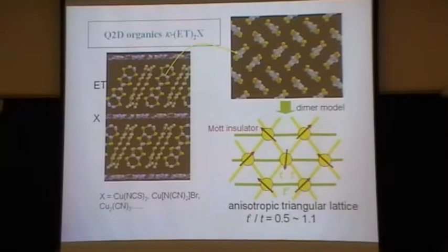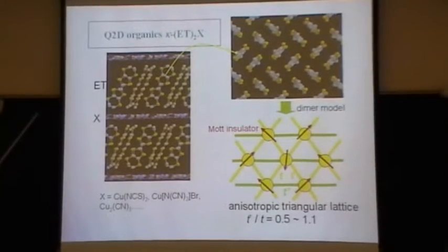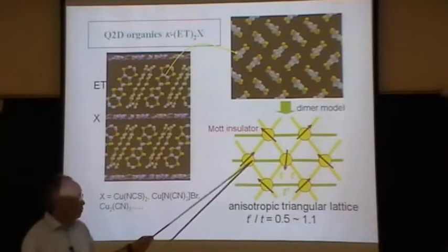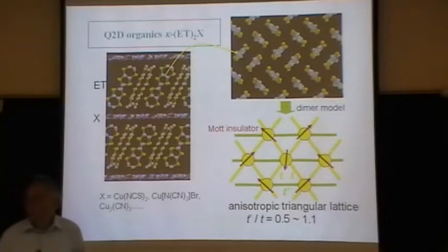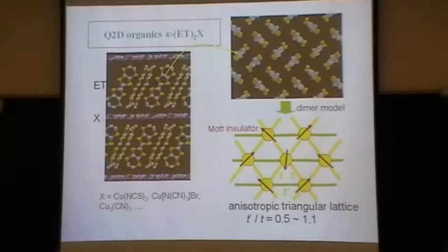I see. Okay. What's the scale of the Hubbard U? Don't know, but the interesting thing about this is that you can drive the Mott transition with pressure very easily. So these things can be tuned to be very close to the Mott transition. Generally, as a rule of thumb, the hopping energy is a factor of 10 smaller than in metals. All energy scales are a factor of 10 lower, and so U also is, presumably, a factor of 10 lower. Moderate. Yeah, instead of 4 eV, it will be half an eV, or even less, because we know that we're in the vicinity of the Mott transition.